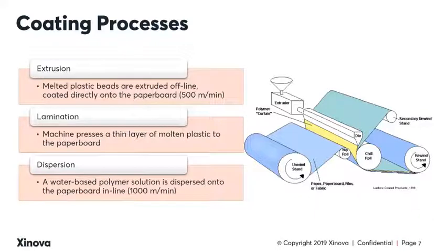There are also many coating processes that are commonly used in this industry. In the figure on the right, you can see the process of extrusion, where melted plastic beads are extruded offline, coated directly onto the paperboard. Coatings can also be added through lamination, where a thin layer of molten plastic is added to the board, or through dispersion, where a water-based polymer solution is dispersed onto the paperboard inline at a much faster speed.